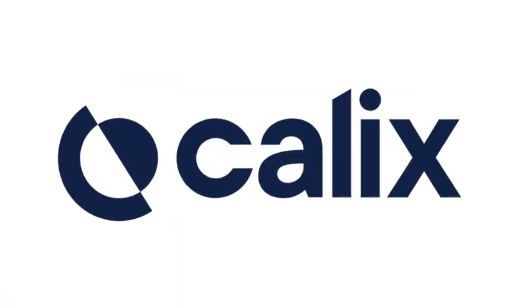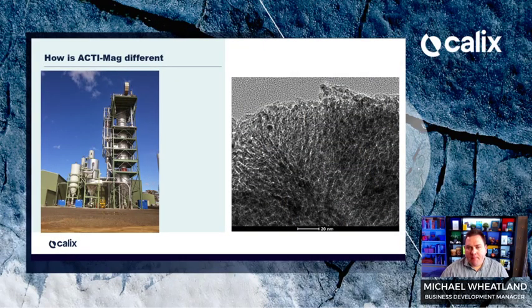Just going back to one of my previous slides here, I'll flick back to it. Just flicking back to this slide, as I mentioned, commodity grade magnesium products like Phoslock or other types of those products are produced in quite a different way, and they end up with a very low surface area. I know commodity grade magnesium hydroxides that we've tested can be as low as 40 square metres per gram, whereas the magnesium oxide we produce for ActiMag can have a surface area that's well over 300 to 350 square metres per gram.